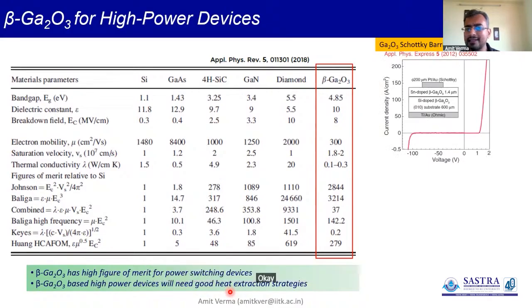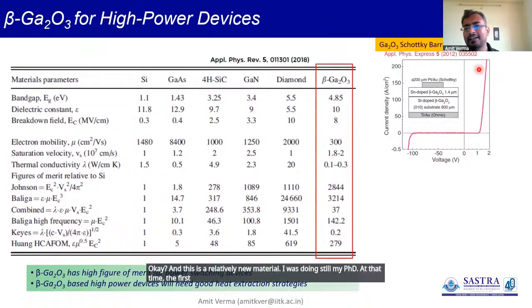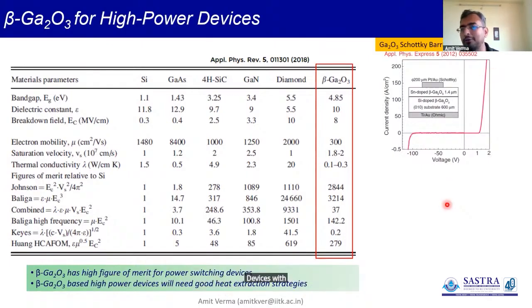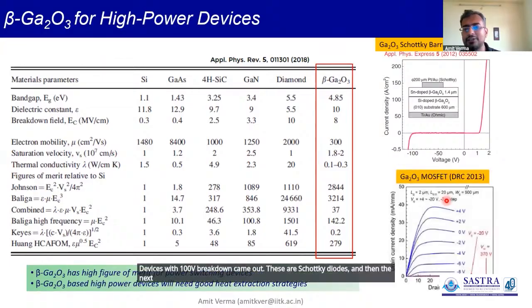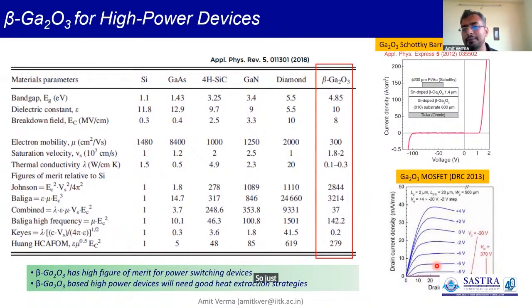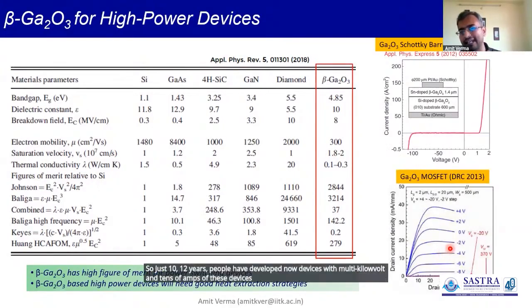And this is a relatively new material. I was still doing my PhD at that time when the first gallium oxide devices with 100-volt breakdown came out. These are Schottky diodes. And then the next year, the first MOSFETs were demonstrated with breakdown of close to 370 volts or so. So in just 10, 12 years, people have now developed devices with multi-kilovolt and tens of amps. So this has developed really quickly.